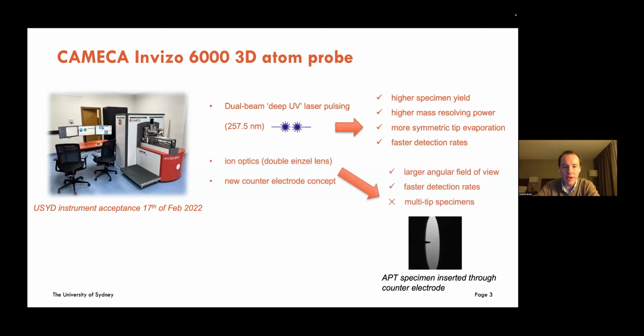The other big advancement here, of course, is the larger field of view, which is enabled through new ion optics with the double Einzel lens and a new counter electrode concept. This also contributes to the faster detection rates, because whereas before with the LEAPs you were losing quite a lot of the ions and they weren't getting through the electrode, now we're capturing a lot more of the tip, potentially the entire tip surface if you tip sharp enough. So for the same equivalent evaporation rate, you're getting a much faster detection rate.